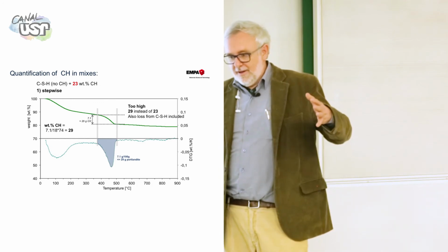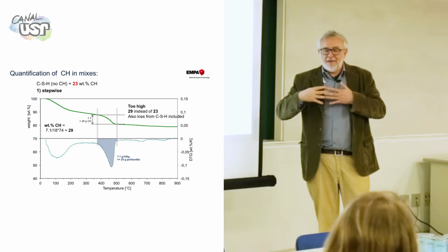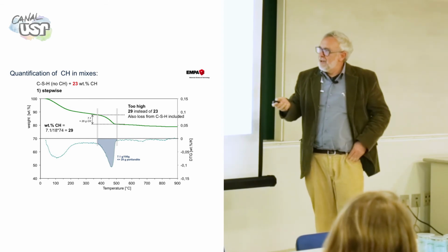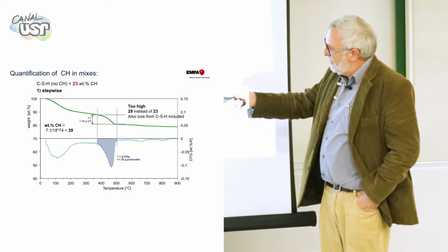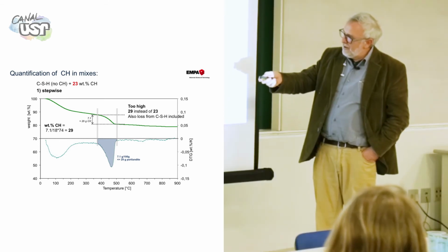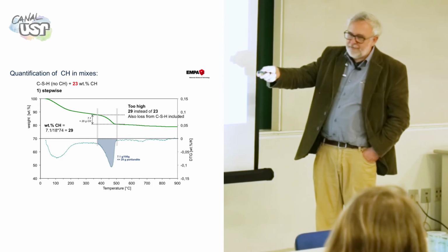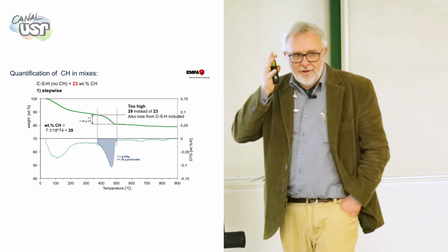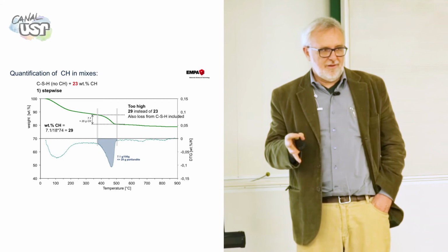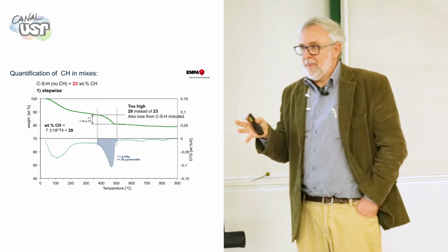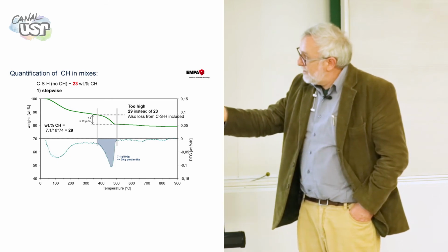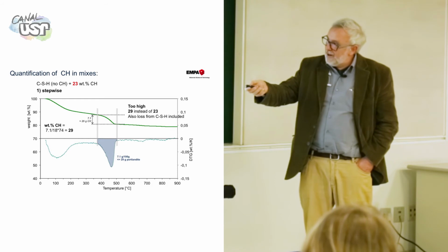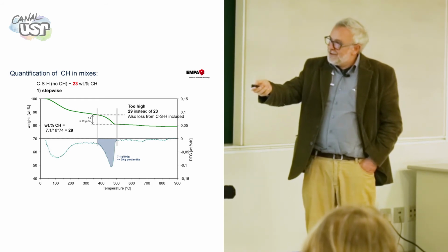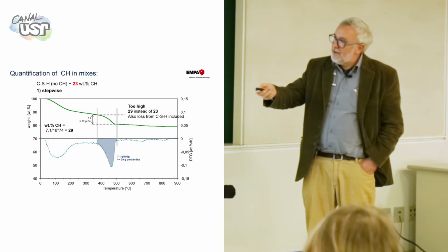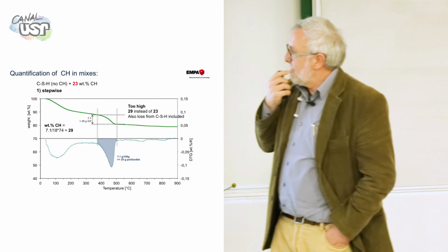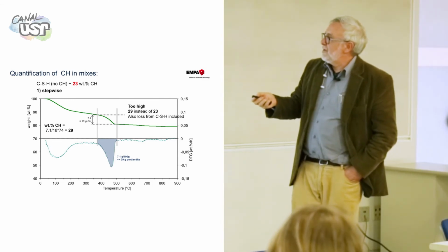Okay? The problem is that the equipment has software to do the analysis. And the default approach is stepwise, which means the onset of the peak is here, so this is 0, the end is here, and then I just measure this difference. This is what the machine does for you by default, most of the machines. If you are using pure portlandite, it's okay. But if you are using cement, it's not okay. Because you see here, it was losing weight before and keeps losing weight after. So this difference is a result of this plus this. There are 2 peaks overlapping. So in this calculation, you got 29%.